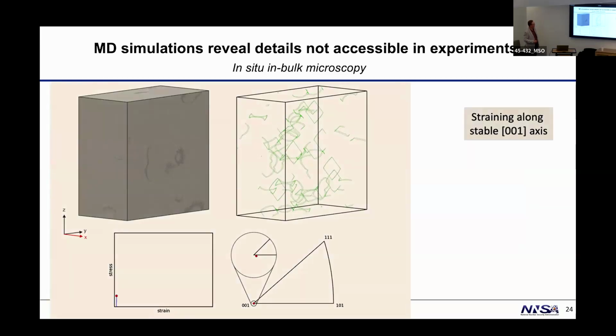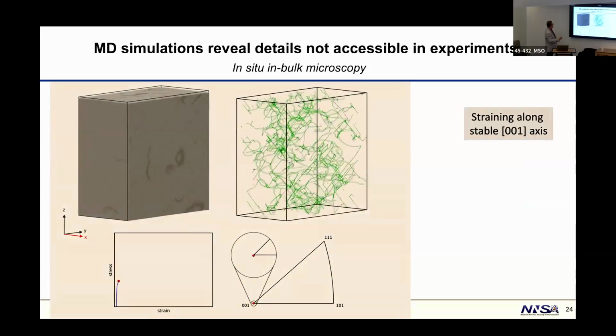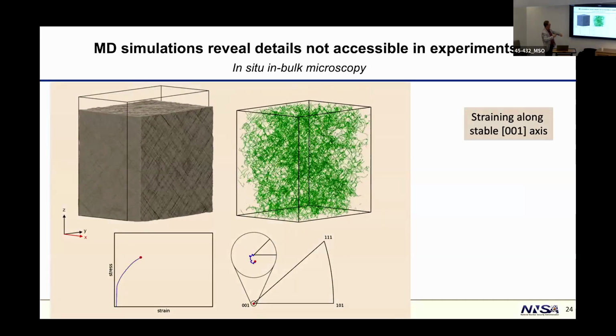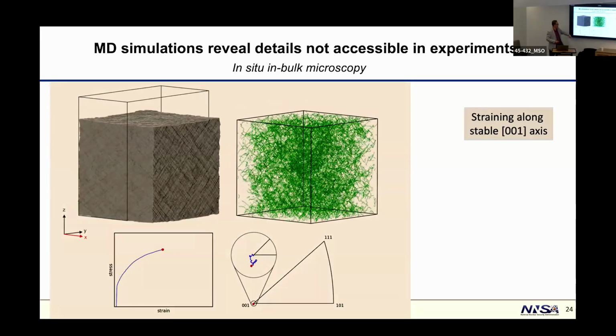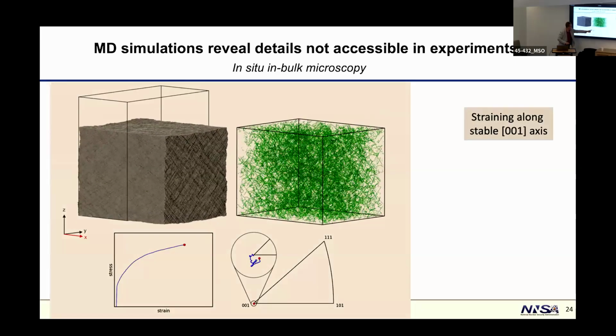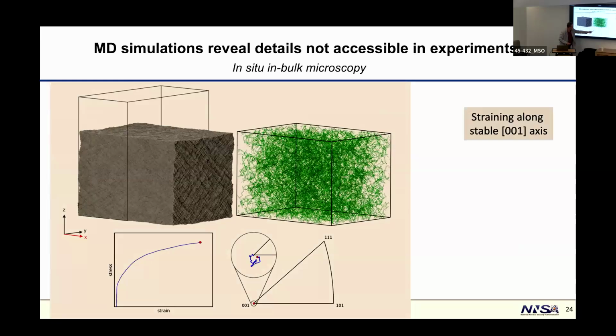So there are a couple of examples. This particular orientation of a crystal, we compress it, okay? No, we pull it actually. It's such that it doesn't rotate. You can see that the orientation axis remains very much aligned with the tensile axis. These precessions are within a fraction of 1 degree, so it basically stays around the same. So it's stable, it doesn't rotate. Look at the curve.